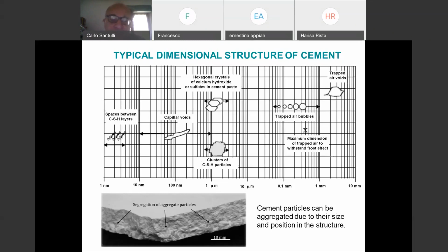And then we can have some aggregation of cement particles, and this might represent a problem, also the segregation of cement particles because they form a harder part. In another sense, they may stop cracks from intruding into them, but on the other side, cracks can move around, and the K can be diverted, which means, in practical terms, that they accelerate fracture instead of stopping it. And this might be due to inaccurate mixing.